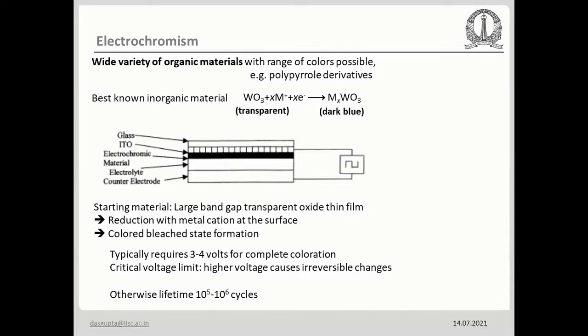In this case, for example, if the material is tungsten oxide, which is a famous material for electrochromism, there are also a wide variety of organic materials, which give a wide range of color. But one very commonly used material is tungsten oxide, which can react with some metal ion. Preferably the electrolyte is lithium based, so lithium goes in, and then you have a lithiated tungsten oxide, which is dark blue. The pure tungsten oxide is transparent. This is also the cross section of the layer, and it goes for even 10 to the power 5 to 10 to the power 6 cycles.